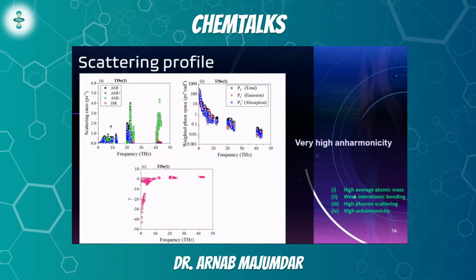Okay. The last criterion was that we need high anharmonicity. So we decided to plot the scattering profiles of all the materials. Here again, I've just shown it for TLSE as a representative, but it's very similar for all the other materials too, whether it's indium sulfide, indium selenide, indium telluride, the thallium series, the gallium series, it's basically very similar. And we see that at lower frequency vibrations, the anharmonicity is actually very high.